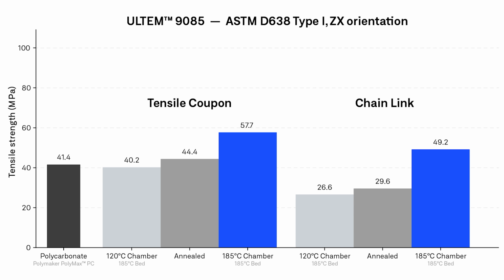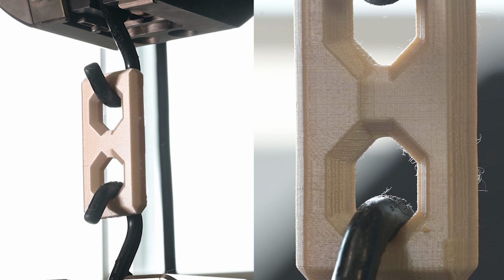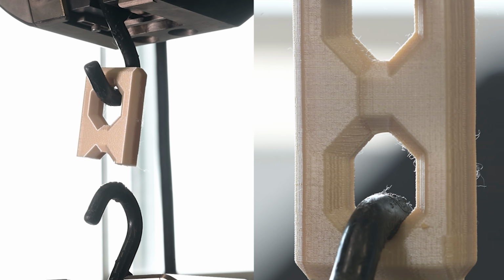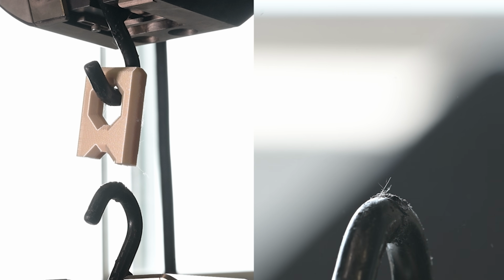Starting with ULTEM 9085, parts printed at the recommended 185C chamber consistently outperformed those at 120C. Tensile strength increased by approximately 44%, with cold specimens performing on par with polycarbonate, a low-cost engineering-grade polymer. Unfortunately, annealing produced marginal increases in part performance and also resulted in a lot of warping. Equally important to strength, the higher chamber temperature improved ductility and demonstrated far better consistency between samples, which is important because manufacturing isn't just about achieving strength once, it's about producing the same result every time.